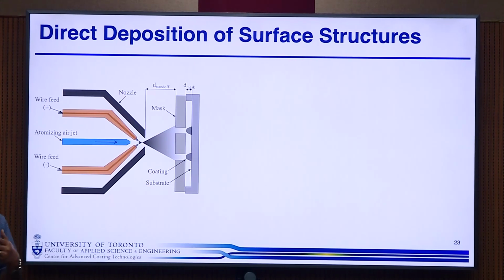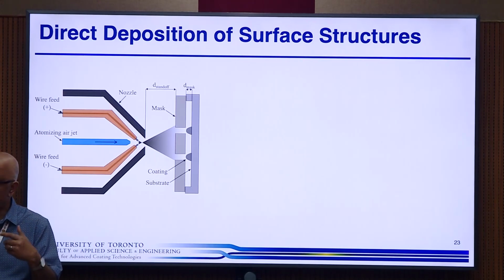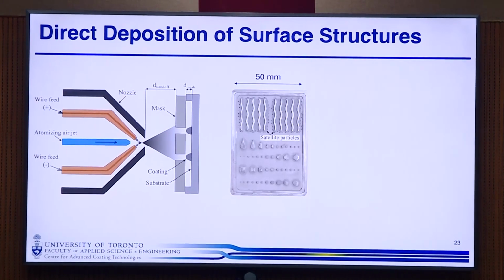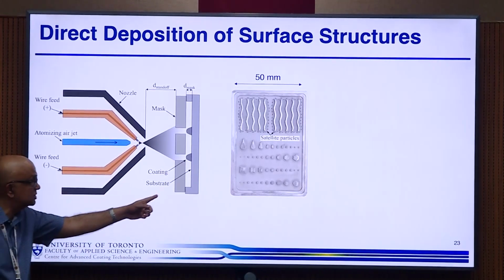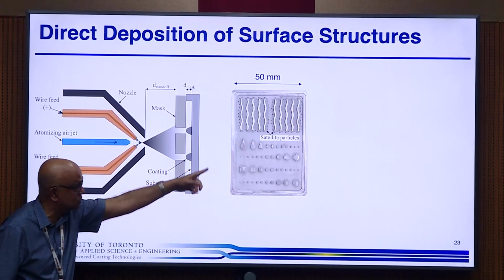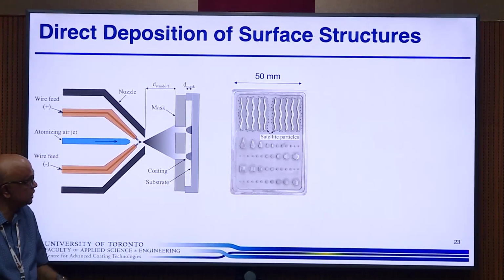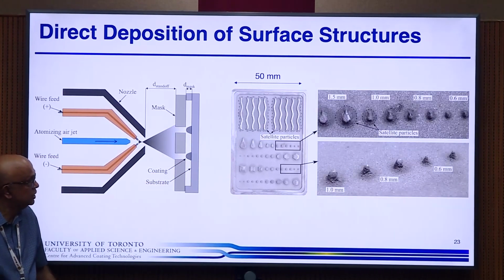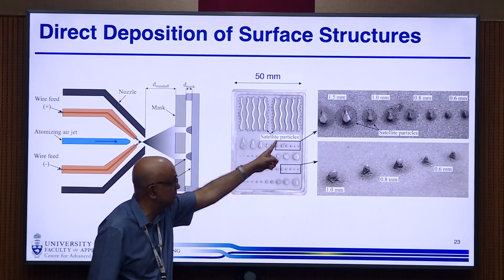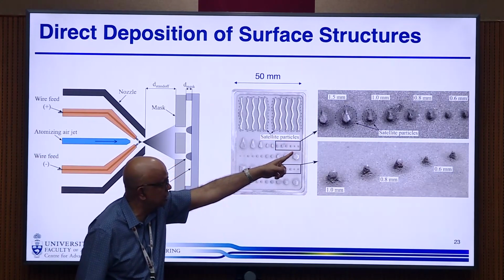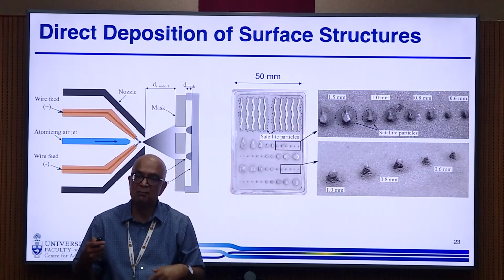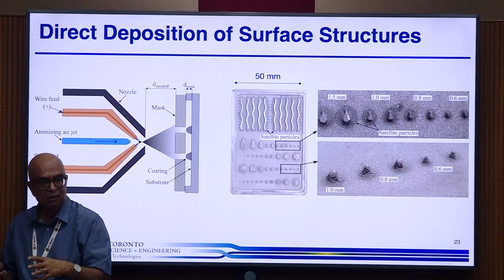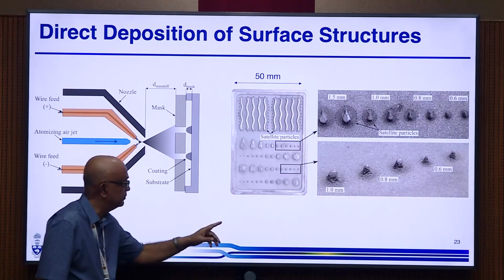But then we said, can we use our spray to make surface features? So now, instead of using our 3D printing as sacrificial, we can make a mask. We can 3D print a polymer mask, right? So we 3D print a polymer mask, and we had openings in all sorts of different shapes. And we wanted to see what sort of resolution we have. So if you look at these ones, there's this little airfoil shape, and something down to about 1 millimeter, you can retain that shape quite nicely.